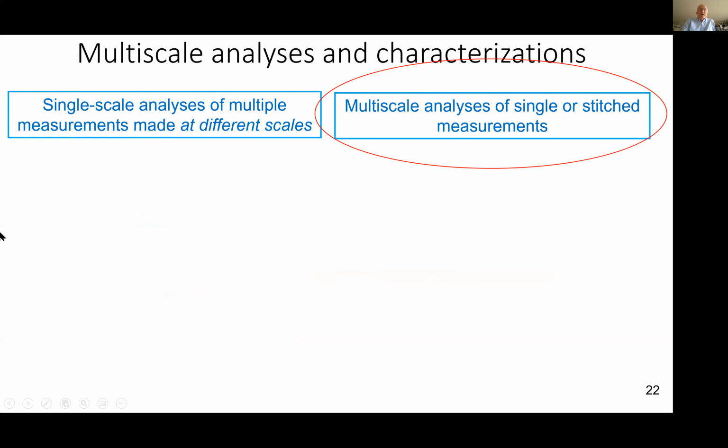So to do a multi-scale analysis, some people think you need to take multiple measurements at different scales. You can, but all of the microscope systems that I've worked with change when you change the lens or even the electronic zoom. And so the multi-scale analyses don't always overlap as we switch the scale. The RA may appear to, but that's because it's so non-critical. So for multi-scale, I discourage this.